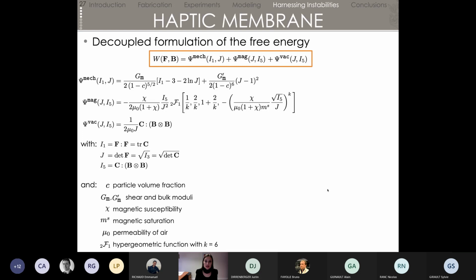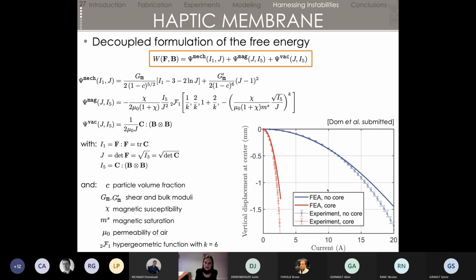The only new thing and thing that's easier is that in your free energy, there's no mechanical invariant that shows up. So you have J here, but you need to talk to Kostas to know a little more about it. Visibly, to make your life easier in finite elements, you will consider your material slightly incompressible, so you don't have some elements locking effect when you're doing the computation. But anyway, it's way easier to identify the parameters of your model. In fact, here on the curve that I showed, they identified the whole behavior on one curve, the blue one, which is just the experiment without the core, and we're able to predict the behavior of the layer with the core.